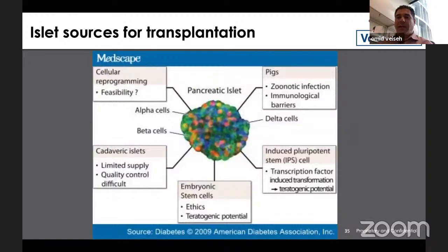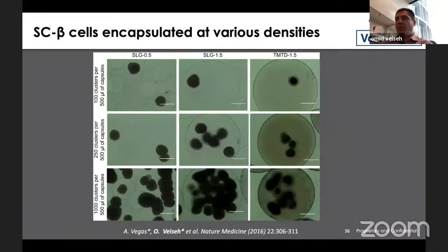So now that we had the right material optimized, going back to the cells, we wanted to load them up with the appropriate cells to come up with a solution for type 1 diabetes patients. There are a lot of cell sources available, but we're really excited about the stem cell derived sources that are now available for use. And so we worked with Doug Melton's group out of Harvard, who had this protocol for taking embryonic stem cells and differentiating them. When we used those cells in our capsules, we first tested them in rodents in different densities and with and without the coated hydrogels.